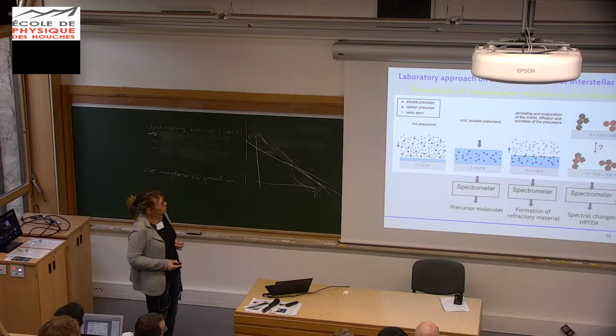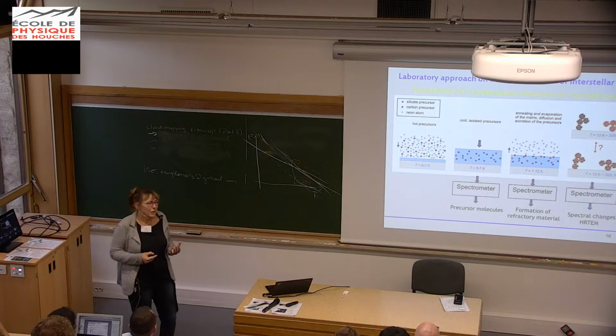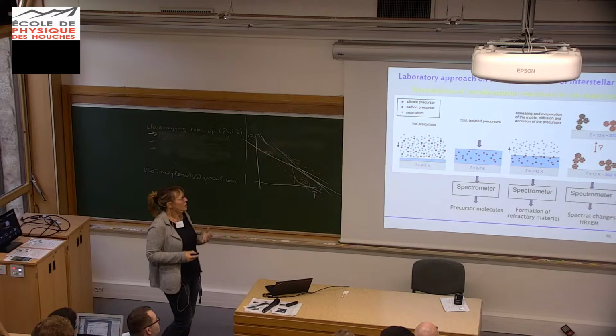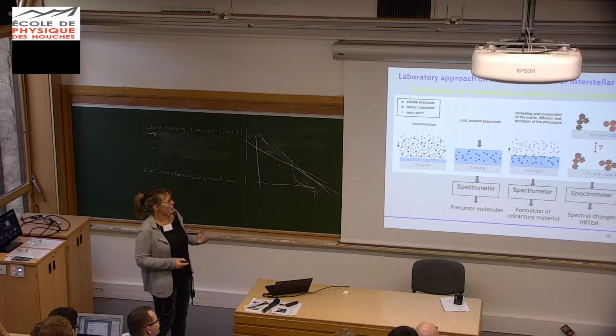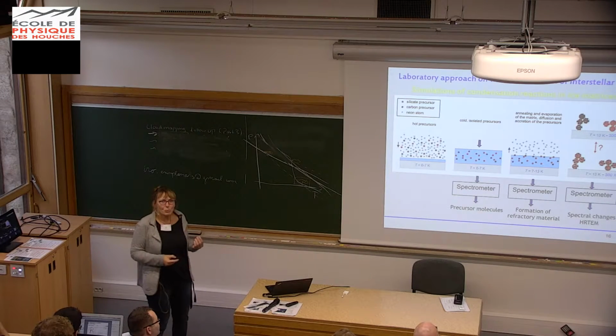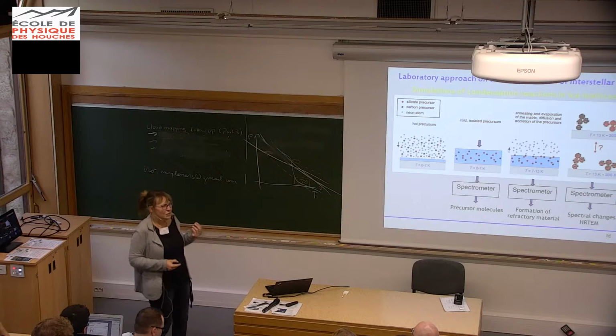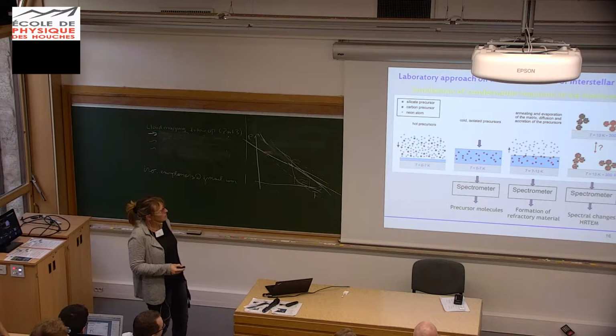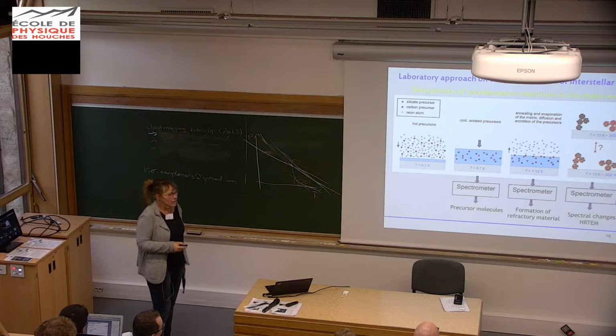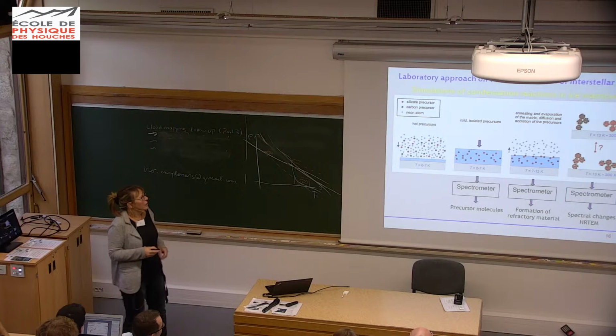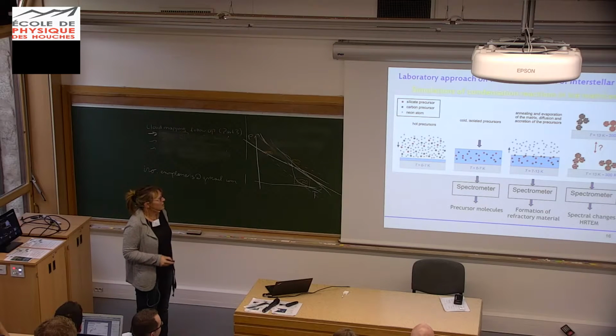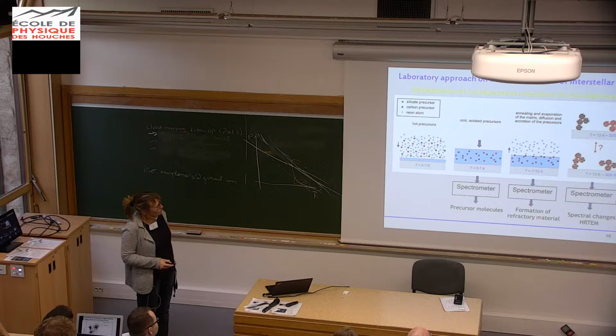And then we apply a kind of trick, because we cannot wait millions of years. So we simply anneal these ice layers a little bit, by 2-3 kelvins, and then we trigger the diffusion of these species in the ice layers, and they can react with each other. Then you can monitor these reactions in situ with spectroscopy, for example with infrared spectroscopy.